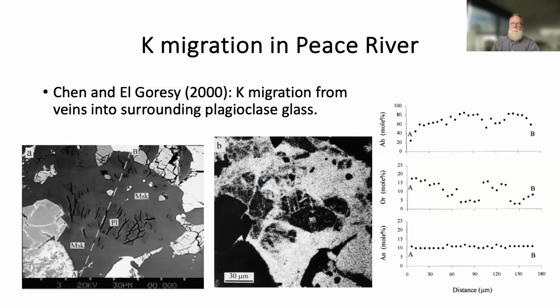So this had been seen before. In 2000, Chen and El Goresy measured high potassium in maskelynites, and they basically documented this process in their paper where they argued that maskelynite isn't really diaplectic glass. They used this to argue that all maskelynite had melted, and this was their evidence. They didn't think about what it meant for potassium-argon dates of the melt vein. Anyway,